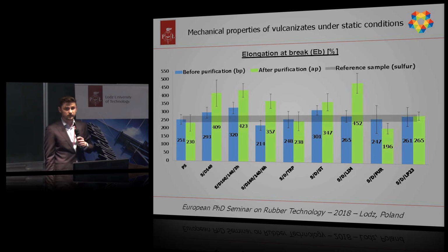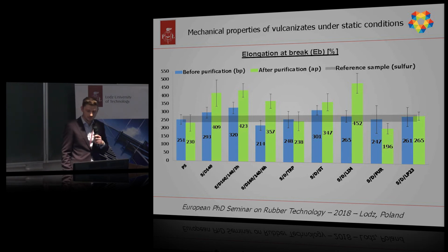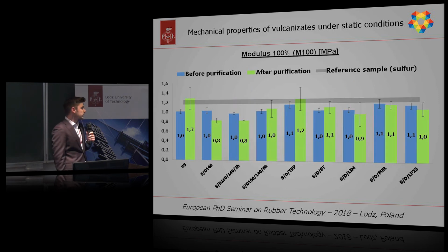When it comes to the mechanical properties of vulcanizates under static conditions, namely elongation at break, we can see that the samples cured with sulfur organic copolymers exhibit a classical dependence between crosslink density and their elasticity, because samples with lower crosslink density exhibit higher elongation at break, and the other way around. When it comes to the values of modulus 100%, we are not observing very significant changes in stiffness of materials, also the classical dependence.